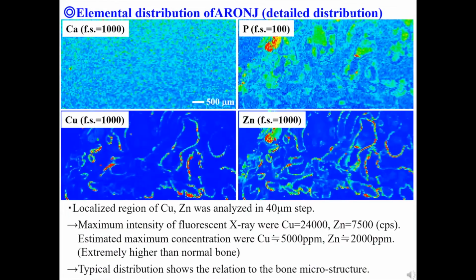Those images are the detailed elemental distribution. Spot size is 40 micrometers. Line-shaped characteristic accumulation of copper was observed in the ARONJ sequestrum, and zinc showed a similar image. The intensity of fluorescent X-ray from copper and zinc were quite high. The maximum concentrations were roughly estimated as several thousand ppm. The typical distribution shows the relation to the bone microstructure.